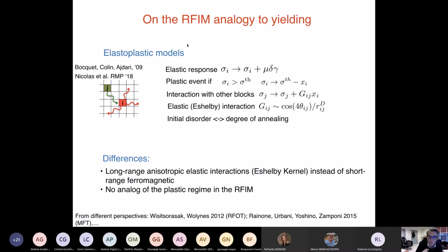So you have really something which is similar to the random field Ising model. At the same time, there are important differences. The most important difference is that in the random field Ising model, once one spin flips, you have an interaction which is short range and is ferromagnetic with all the neighbors. Here you have a plastic event at a certain site i, sigma_i goes down, and then the stress is redistributed using this kernel, this interaction G_ij, which is anisotropic because there is cosine of 4 theta, and also quite long range because there is this 1 over r to the d.